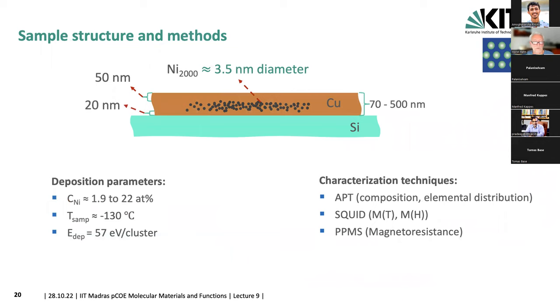So these are the deposition parameters. We changed the nickel concentration from 1.9 to 22 atomic percent. The substrate temperature during the deposition was held at minus 130 Celsius, and the deposition energy was around 60 eV per cluster. And these are the techniques which we used: structural characterization by APT, SQUID magnetometry for learning about the magnetic properties, and also a physical property measurement system for magnetoresistance of this material.